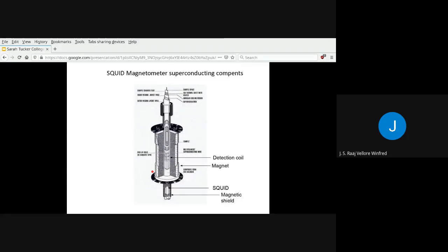Superconducting magnets function at very low temperatures. They go into superconducting mode at around 4 Kelvin. And then here you have the SQUID, which would detect the magnetic field of your sample. And this is a magnet here, and this magnet is what is used to apply very high magnetic fields.